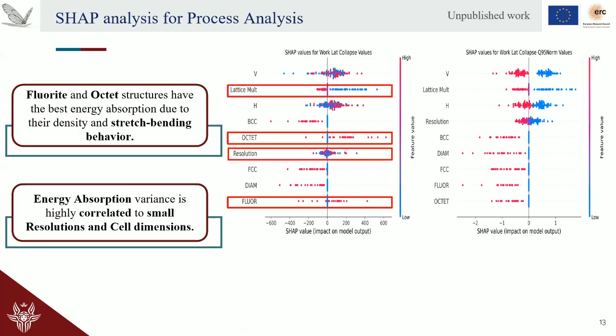We can see also an interaction with the lattice cell size. So a small cell size increases the overall toughness, but we see a lot of noise here in the resolution, hinting that the resolution is interacting with other parameters. And I'll show you in the next slide what is interacting. But what is interesting is that the scatter also increases both by decreasing the cell size and by decreasing the resolution. And that's very counterintuitive because we are increasing the overall toughness, but we are also increasing the scatter. So our specimen is much more prone to defects.